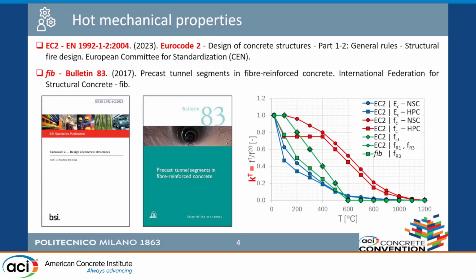Also because in general you see that moving from the circle to the square, we move from lower grade concrete to higher grade concrete, we have a decrease for the Young modulus and also for the compression stress, while the opposite we have for tensile stress. So we have to understand if this works. We have to remember that this is for hot condition.